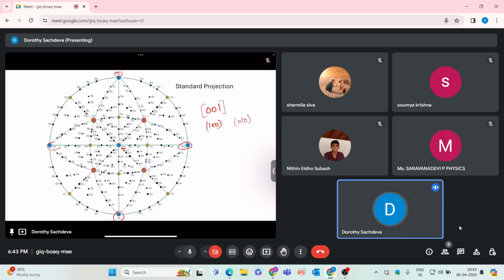and in between these two, 1, 0, 0 and 0, 1, 0, you will have 1, 1, 0. So similarly you can have all the family of planes which will be present in this 0, 0, 1 zone axis. So 0, 0, 1 zone axis means all the planes which are perpendicular to this zone axis will be present in this diffraction pattern.